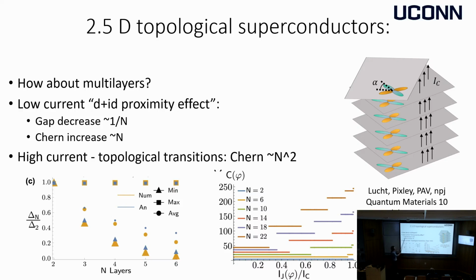competing effects. On the one hand, your gap, which is formed essentially due to this interface, is delocalized, is smeared out throughout this flake. It proximitizes all of it, that's true, but the average gap goes as 1 over the thickness of that many-layer system, so 1 over the number of layers. On the other hand, the number of edge modes grows as you get more and more layers. So actually at intermediate temperatures, not where the quantized plateau is, the thermal Hall effect, for example, will be independent of thickness. And also, if you measure at the top layer, we found at least numerically for a few layers, the topological gap that you will see at the top layer is pretty much independent of the number of layers you put in.